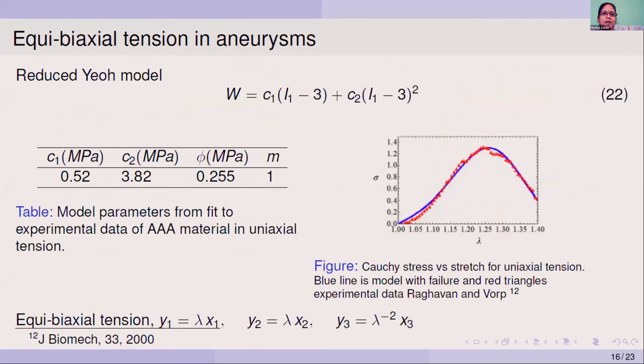So next, another problem of practical interest is to study the onset of damage in a sheet of aneurysm material under equibiaxial tension. Here, in order to describe the intact material behavior, we use the reduced Yeoh model. And here also we get these model parameters from the fit to experimental data of abdominal aortic aneurysm material in uniaxial tension as obtained by Raghavan and Vorp.